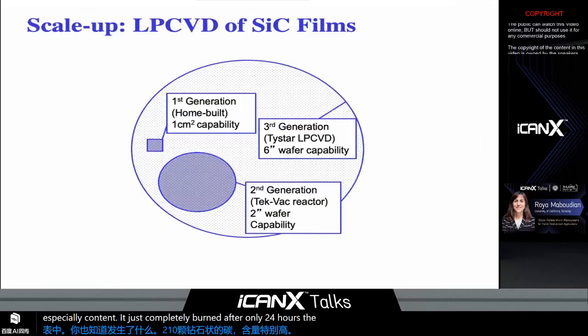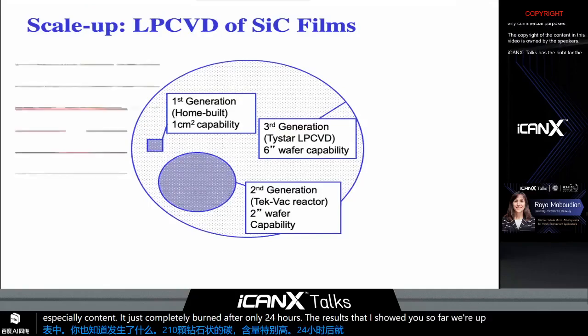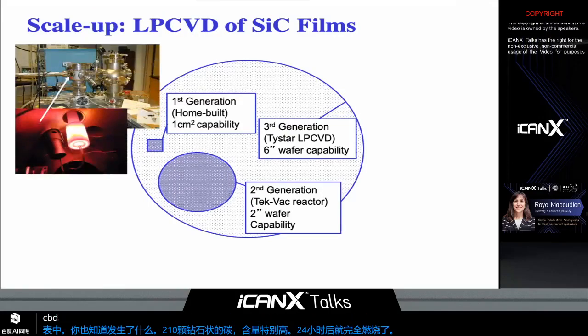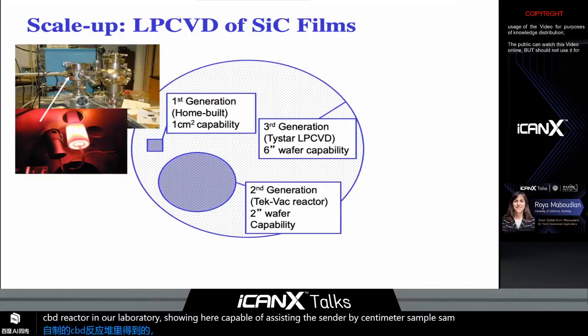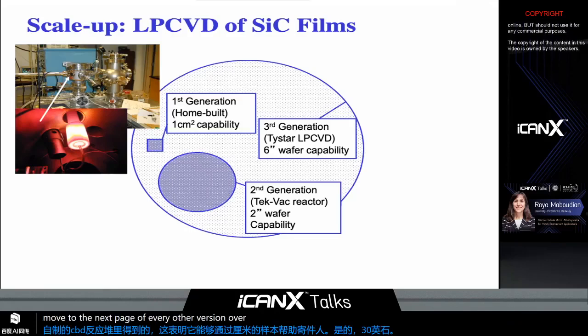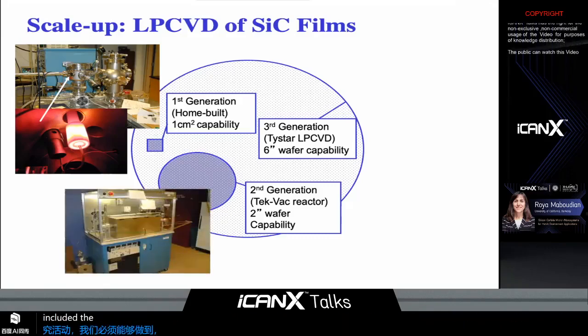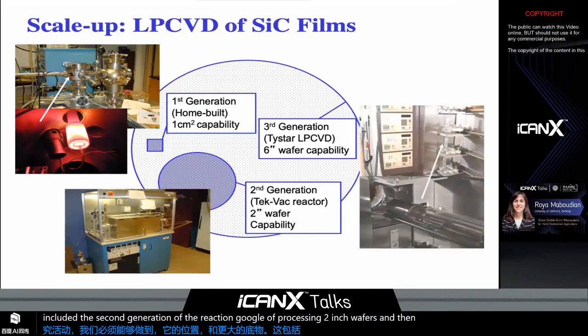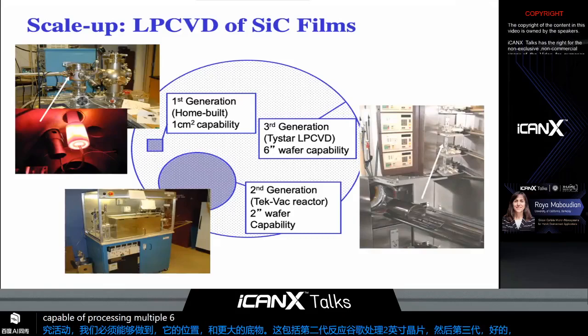The results that I showed you so far were obtained in a home-built CVD reactor in our laboratory, shown here, capable of processing a centimeter by centimeter sample. With these promising results, to move to the next phase of our research activity, we had to be able to deposit these films on larger substrates. This included the second generation LPCVD reactor, capable of processing 2-inch wafers, and then a third generation LPCVD reactor capable of processing multiple 6-inch wafers, which is currently housed in the Berkeley Nanolab.